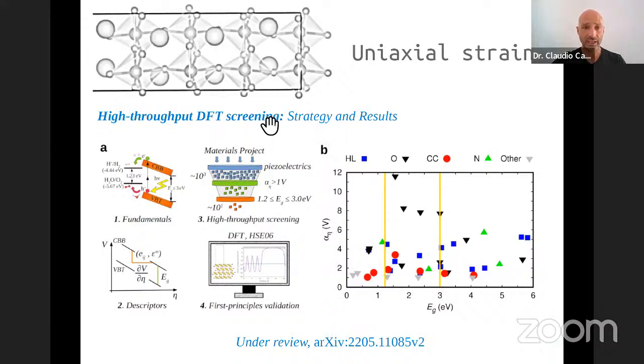right? So this is what we did. So basically, we went to the Materials Project database, where there is a dedicated piezoelectric sub-data set of about 1,000 materials, right? And by using some public, freely available tools, we performed some high throughput runs, right? So basically, we sifted those piezoelectric materials that exhibited an alpha eta coefficient larger than 1 volt, right?